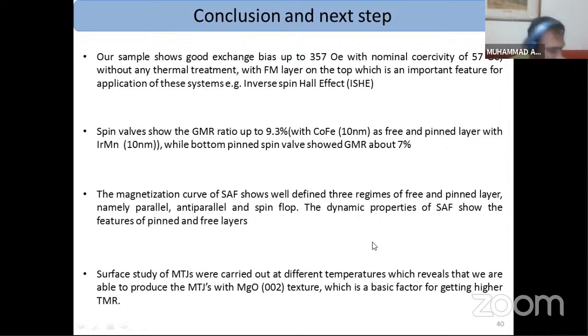The magnetization curve of SAF shows well-defined three regions of free and pinned layer, namely parallel, anti-parallel, and spin flop region. The dynamic properties of SAF show good features of a pinned and free layer. Surface study of MTJs was carried out at different temperatures, which reveals that we are able to produce MTJs with MgO 002, which is a basic factor for getting higher TMR.